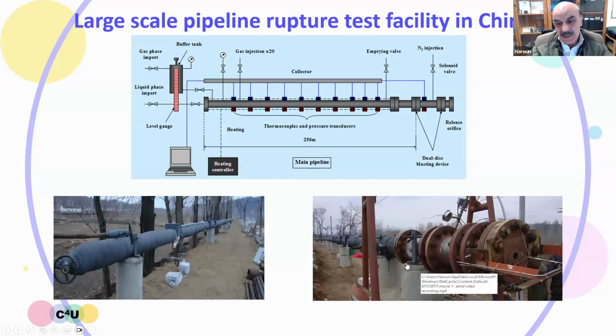One of the important aspects of our work is also the safety aspects when it comes to transportation of CO2 in pipelines. You're dealing with huge amounts of CO2, which is transported. CO2 is, of course, hazardous at concentrations of around 10% per volume, and if it is released, it can be extremely hazardous. As part of this study, we have constructed the longest fully instrumented test pipeline in China, where we have conducted CO2 release tests in order to track the dispersion profile of the CO2, how the concentration of CO2 in the event of an accident changes with time as a function of different impurities, and develop safe working distances.